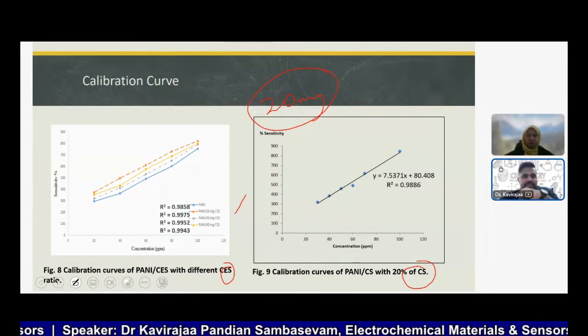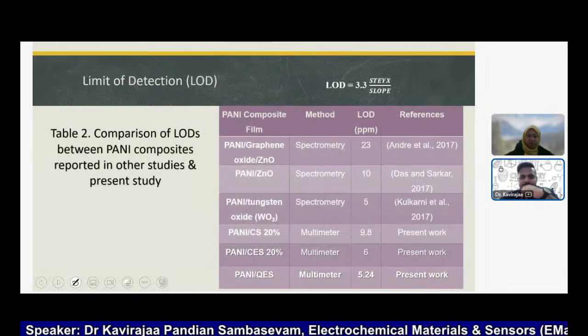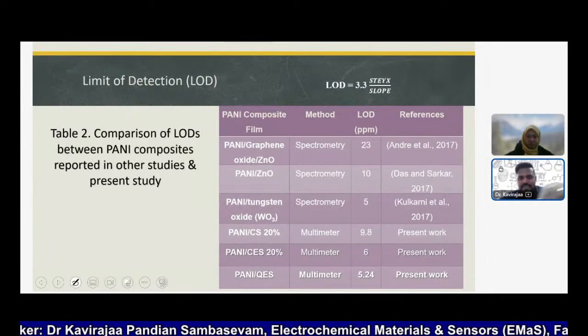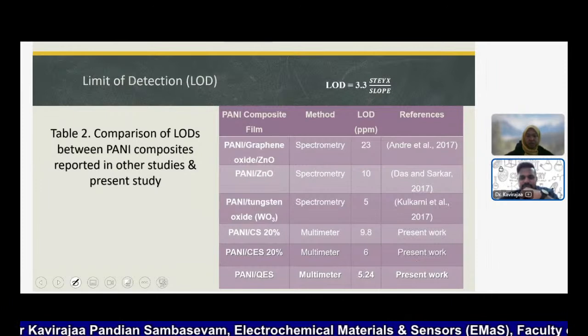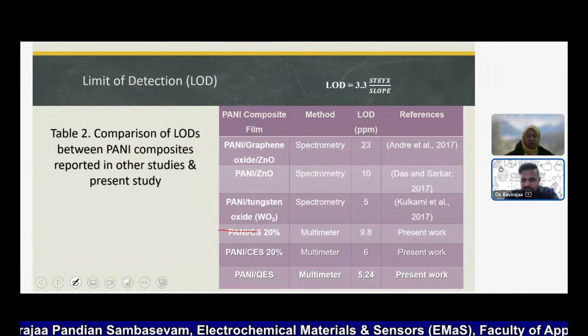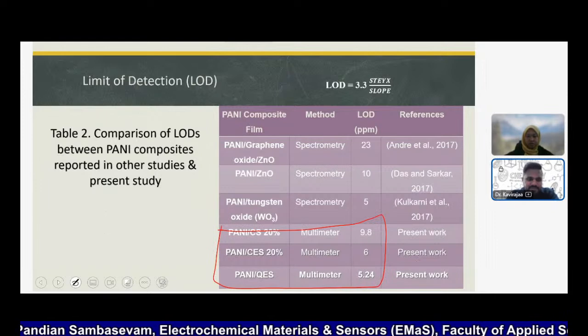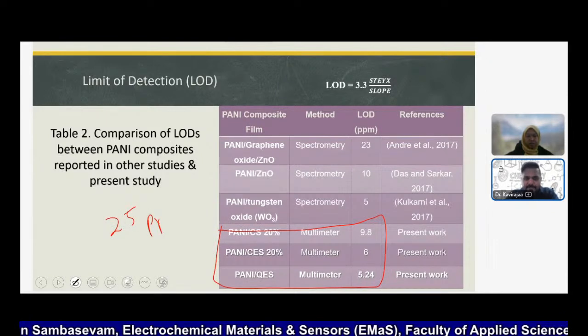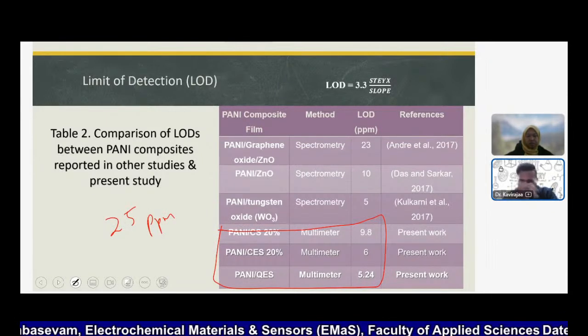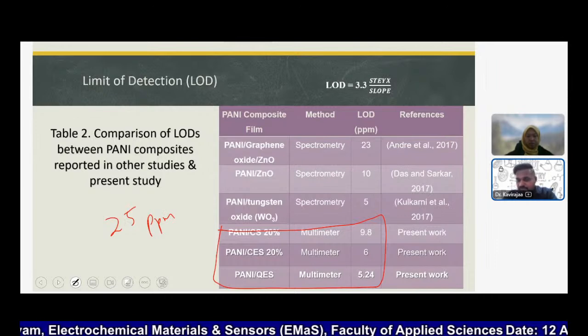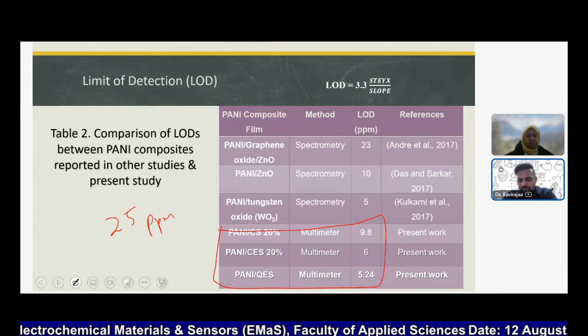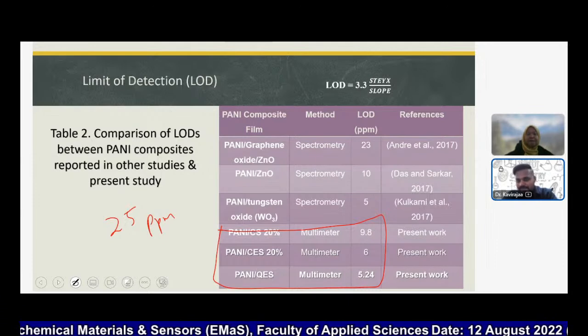So we further the study with other parameters to calculate the limit of detection from the calibration curve. So here we can see the threshold for the ammonia, as I mentioned earlier, is 25 ppm. So we managed to get lesser than the threshold value. So in a very simpler manner, I feel like this is good.